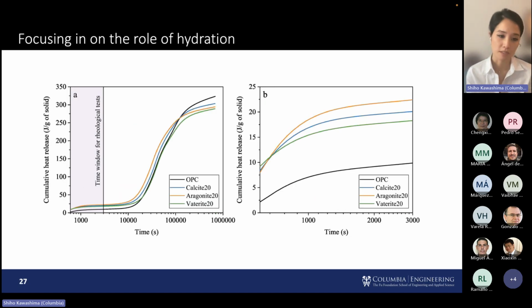Now let's look at the cumulative heat release. So again, these are similar results from before, but now let's really focus in on the time window for the rheological tests. So remember that when we looked at it before, calcite actually, and this is by weight of solid, okay? So that's important. We're looking at the entire solid system. We're not just normalizing it with respect to cement. So this will give us an indication of basically the formation of early hydrates, right? And that's why this is also taken to be an indication of mechanical properties.